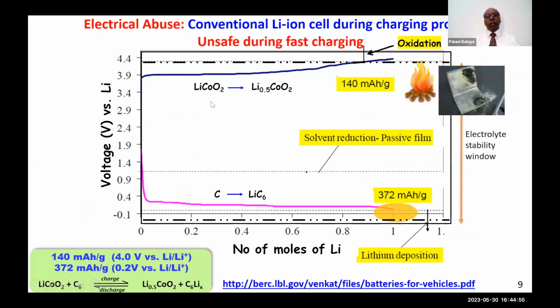Okay. Now, the second abuse can be quick charging. If I do a quick charging of a particular chemistry, for example, lithium cobalt oxide versus graphite, I can see that while charging, what is happening is we are removing the lithium ion and electron, and cobalt gets oxidized. Co3+ becomes Co4+. Whereas here, say 3+ becomes 4+, sorry. Whereas here, in the carbon, lithium is intercalated and there is a reduction reaction. So this reduction reaction happens at 0.2 volt versus lithium, which is 0. This dotted line is the 0. It is happening at a potential close to lithium metal deposition, lithium metal formation. So if you do fast charging, because of the polarization and internal resistance we discussed previously, this 0.2 volt can approach 0 volt.